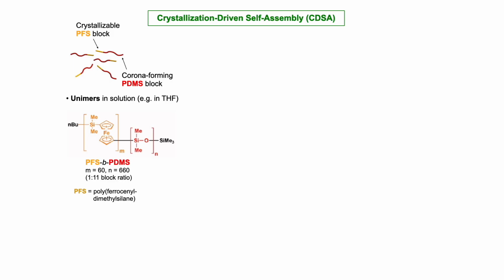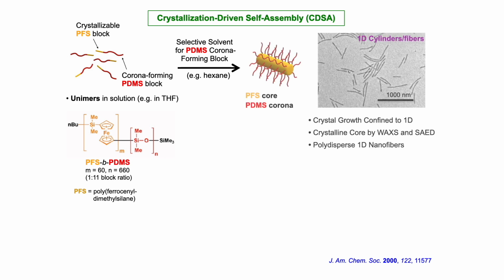The first step is exactly what I showed you on the previous slide. You take a block copolymer such as this one, where you have a crystallizable core forming block. This block forms the corona or shell, and you self-assemble this in, for example, hexanes. And this gives you fiber-like micelles, as I've shown you, where they're all different lengths. There's no control over length here.